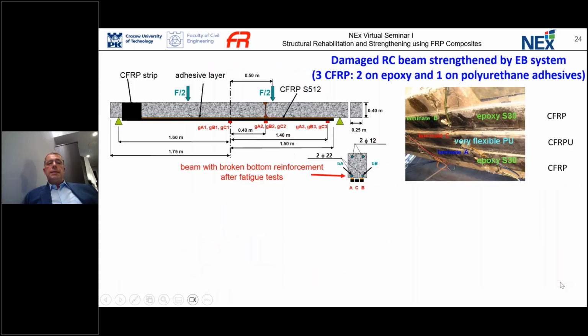So let me say something about additional safety. This is an experiment on a beam that was failed by fatigue tests. After this fatigue test, the lower tensile reinforcement was broken. So after reconstruction, the strengthening and tensile forces were carried out by 3 carbon fibers. 2 of them were bonded with epoxy resin, stiff epoxy resin, and 1 with very flexible polyurethane.